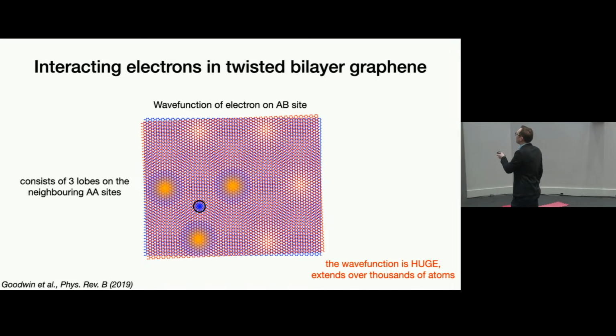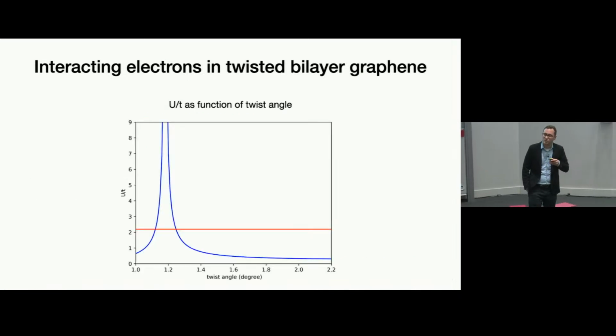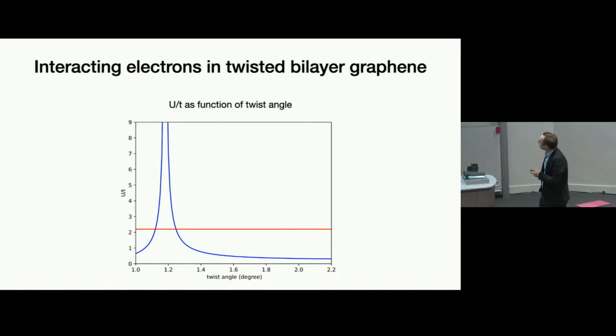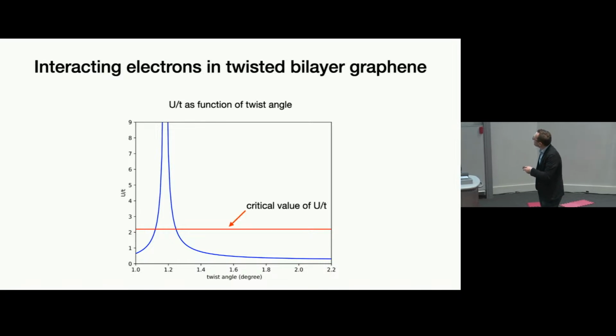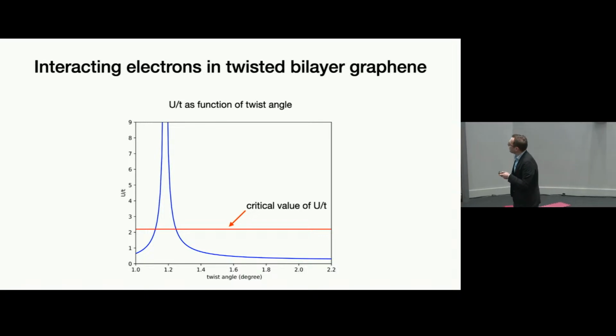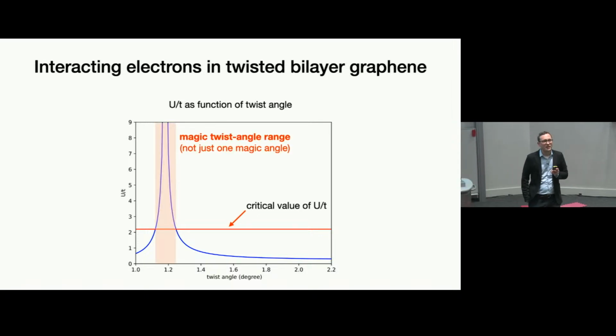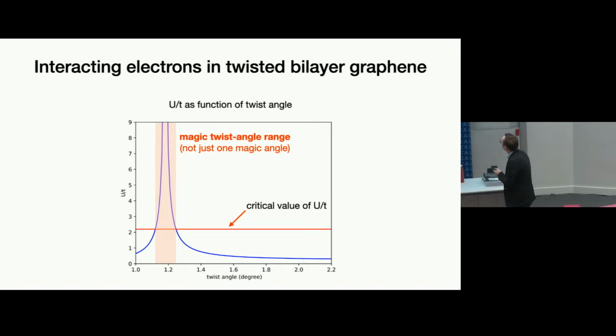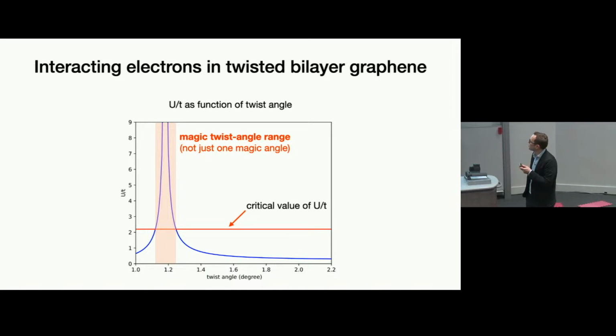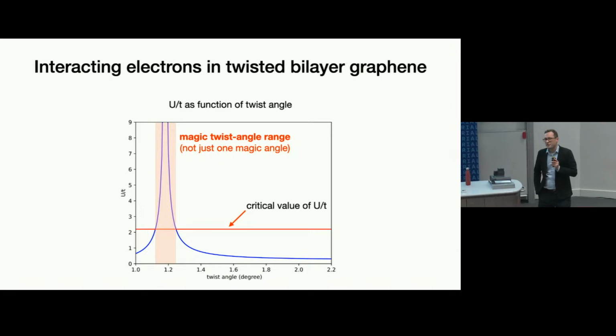So having that wave function, we were now able to calculate the ratio of U over t as a function of twist angle. So this is our result here. And when that ratio exceeds a certain critical value, which is about 2, the material becomes an insulator. The first insight from our calculation was actually, there's not just one magic angle, there's actually a whole window, a whole range of magic angles where you should see insulating behavior. That was our first observation. But then we realized we had actually forgotten something.